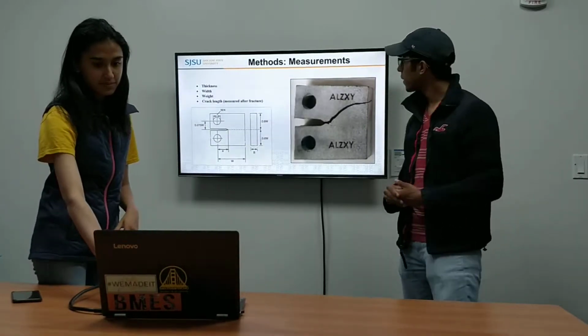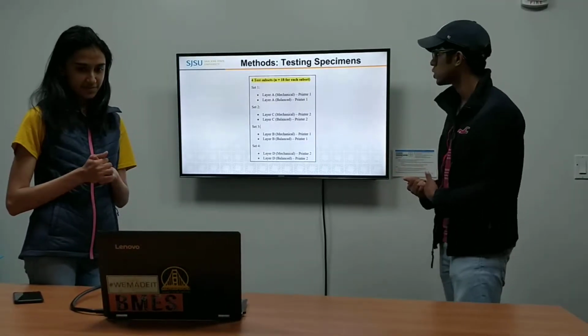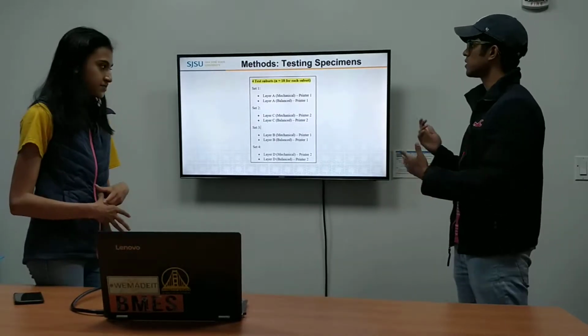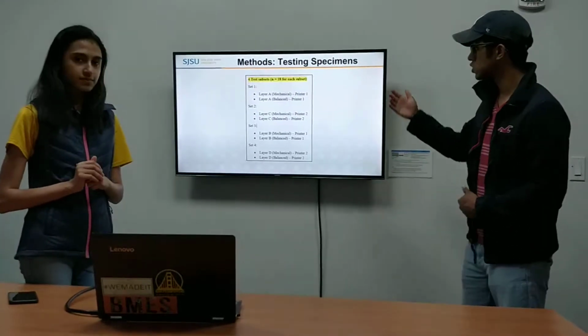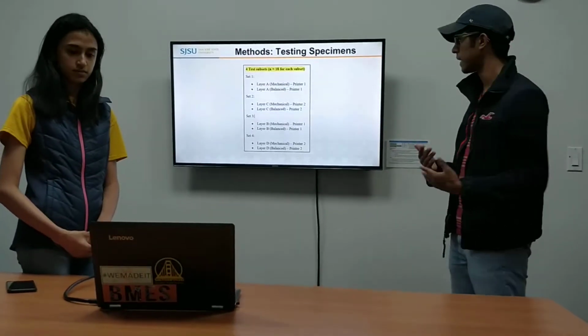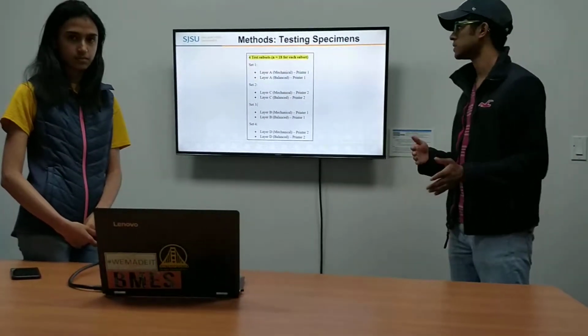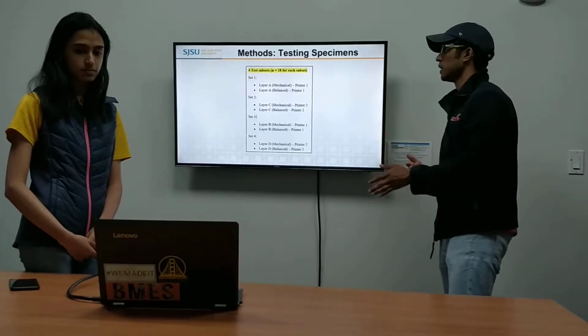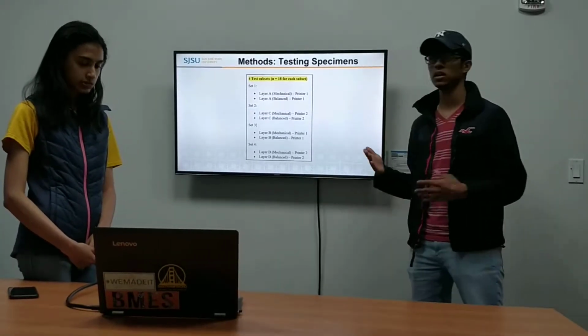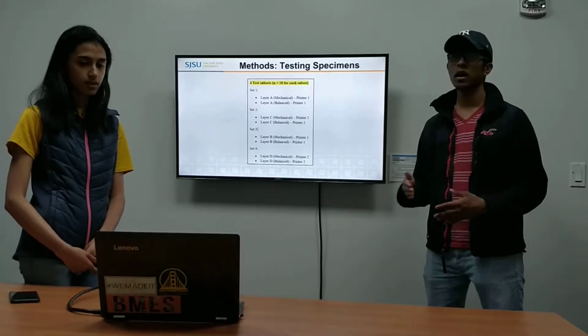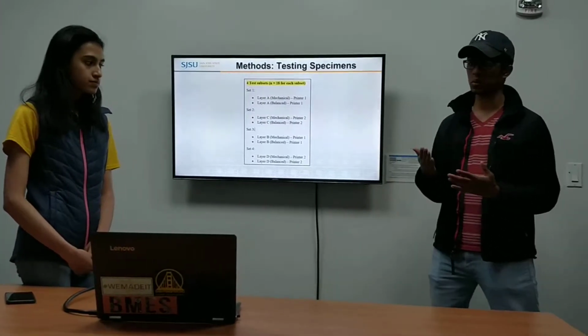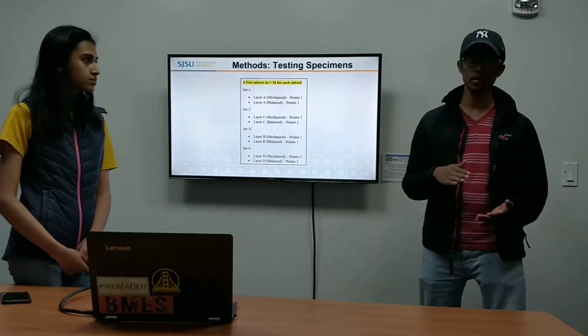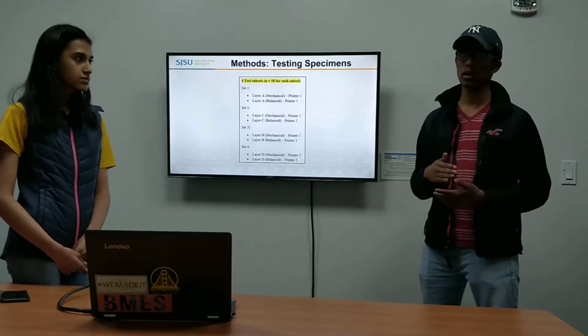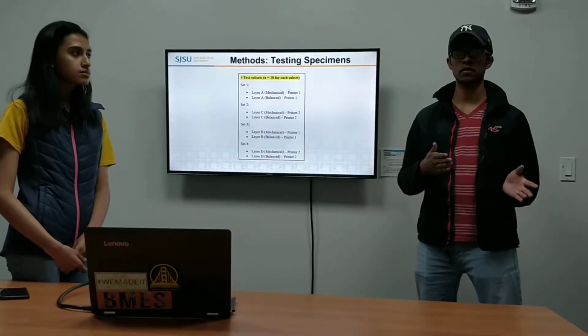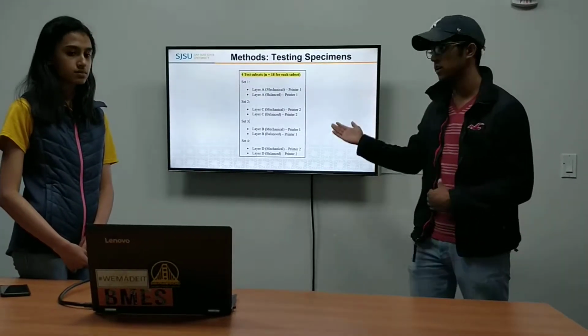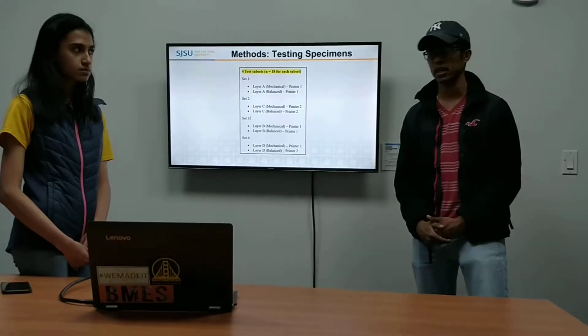And testing specimens. We decided to test our specimens by layers. So we decided to do layer A of mechanical and layer A of balanced, and that was set 1. Similarly, we decided to do set 2 after that with layer C, both balanced and mechanical. What we were thinking was to do a set of 9 samples from mechanical and 9 from balanced from one layer. So even if we do something wrong or find we should have done something differently, we still have another set that we can use to repeat our test.